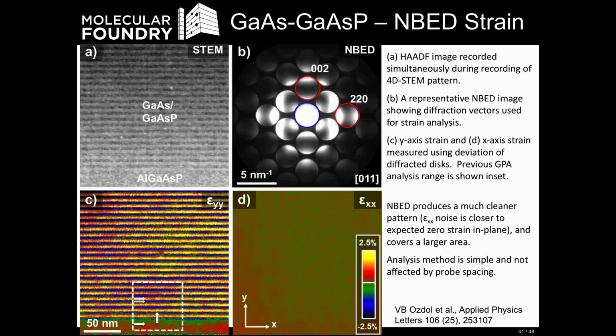And so that's what we've done on this same multi-layer sample here. On the upper left, this is the conventional image formed just using the STEM annular dark field detector. And you can see the multi-layer stack here. But for each one of these pixels, we have a full diffraction space image. And the average one of those is shown in panel B here, the mean average pattern.